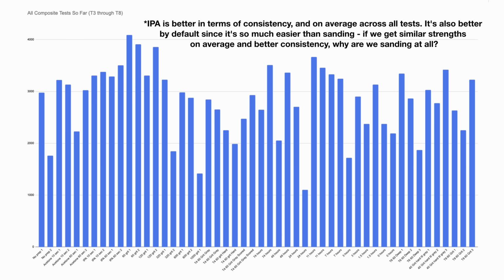Okay, sidebar over. We aren't getting back to 4,000, and if we do, I don't think it's valuable because we can't do it consistently. I'm trying everything I can at this point in the project, and I can barely get these samples to break 3,000 newtons, just 75% of our theoretical and demonstrated maximum. I mean, just by the numbers, the IPA alone, no sanding, is performing better. So like, maybe there's something I'm missing here.